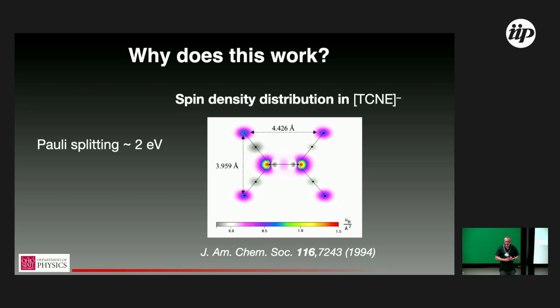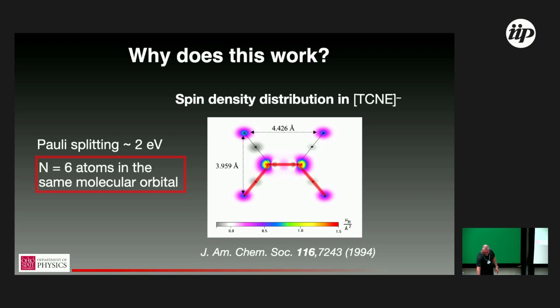This takes me back to the question of why does this work, and this is a little bit hand wavy. This is a measurement of spin density just in TCNE, just in the bare molecule, and what this is effectively representing is the molecular orbital of the pi star electrons, the pi star orbital in the TCNE that lives predominantly in the carbon-carbon double bond in that backbone structure, but hybridizes strongly out to the nitrogens at the end. So that means that this same counting of 6 atoms between the 2 vanadium, this is where our heuristic led us astray.